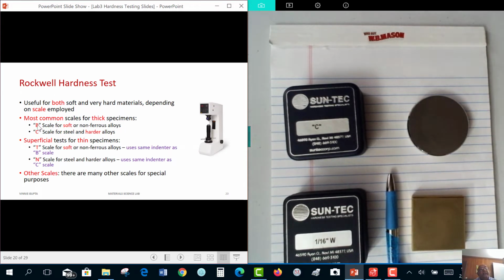So the Rockwell hardness test is useful for both soft and very hard materials. So obviously you are going to choose a different scale. For thick specimens, the most common scales for metallic materials: B scale for soft or non-ferrous alloys. Non-ferrous means where iron is not the predominant element, such as aluminum, brass, copper. We use B scale. C scale is used for steel and harder alloys. So we are going to use C scale for our demo samples, and you're going to apply B scale for your brass sample.